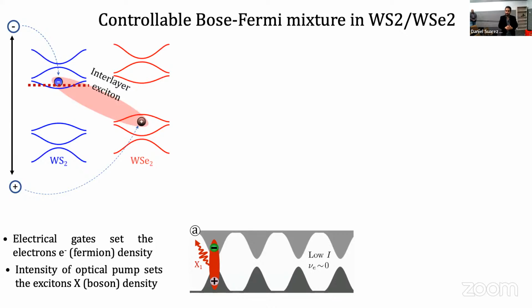Okay, so what you're saying is that if I had this magical system where I could independently control the carriers in each layer, I could do this, but I could do more? Yes, and I think that there are works. For example, I remember from Atac Imamoglu, they isolate one layer from the other with a very thin layer of an insulating material, hBN. In this case, they can independently tune the density on each monolayer, and very fun physics comes from there. And then they can create something that looks like this. In other words, something that looks like bosons and fermions because of the interlayer.